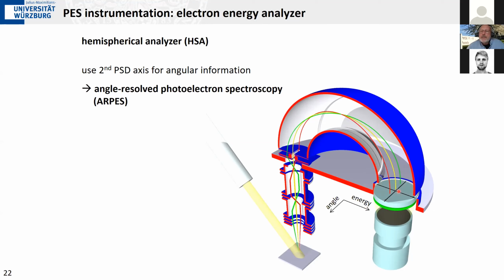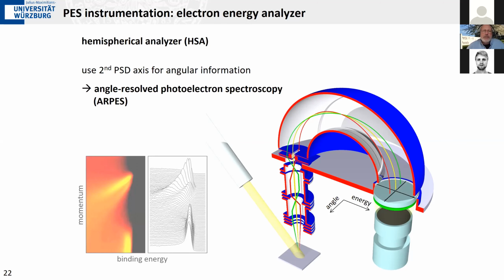So this axis is our energy axis, but you can see that different escape angles are now imaged onto different positions in this direction here. So this direction encodes the angle with which the electrons have come out of the sample. And that is nothing else than the momentum information that we can record from our electrons. And that allows you then to simultaneously measure energy and momentum and map out a band structure, for example. So this is energy, this is momentum, and then you see that you have certain energy versus momentum dispersions and bands.